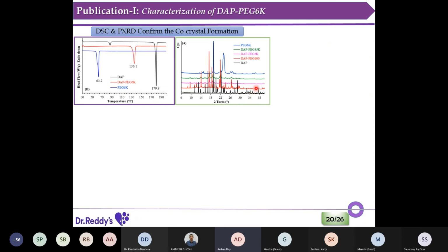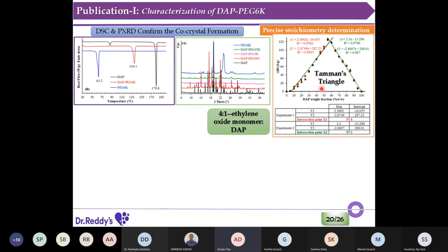And if you see the powder XRD, there are so many unique peaks that arise, and you can also note that the powder XRD patterns of the different grades are mostly the same, with the only difference in crystallinity. But one of the challenges for any co-crystal is determining the stoichiometry. This is not at all straightforward with polymer excipients. So we did it a different way, and it turns out right, that I'll explain.